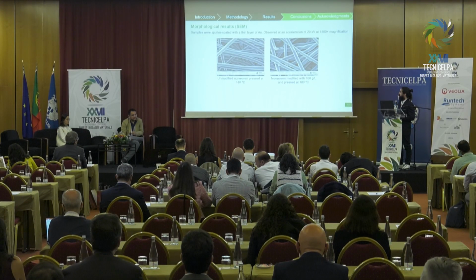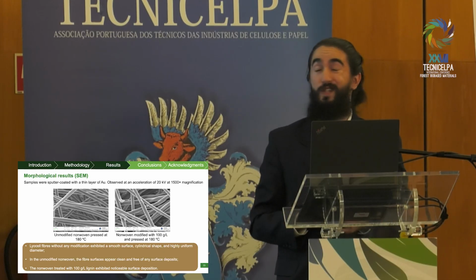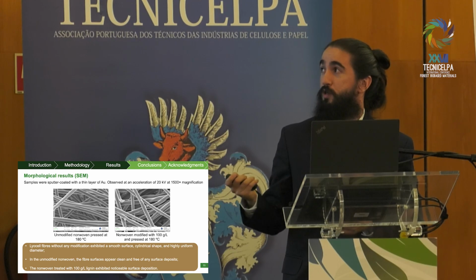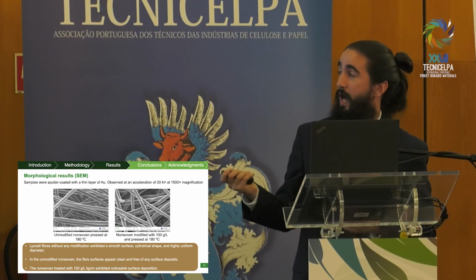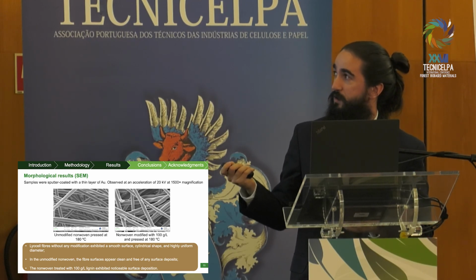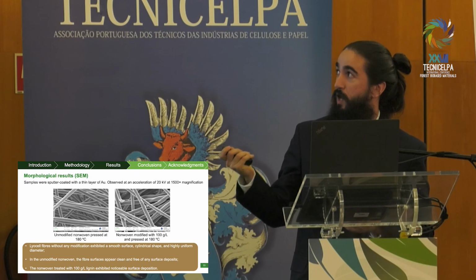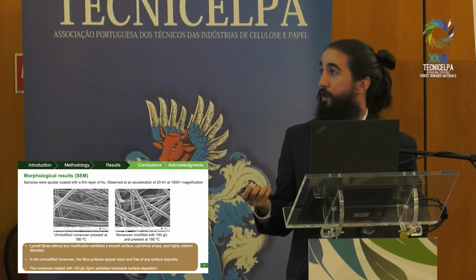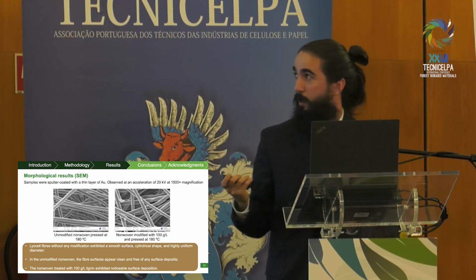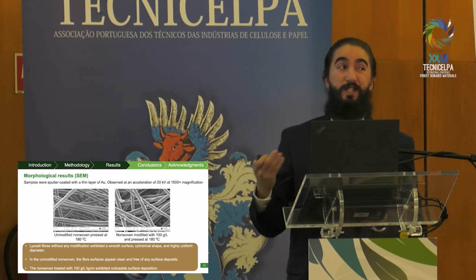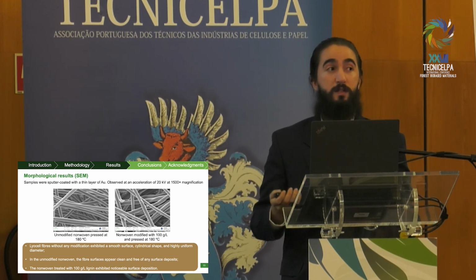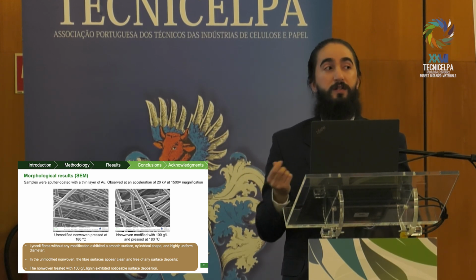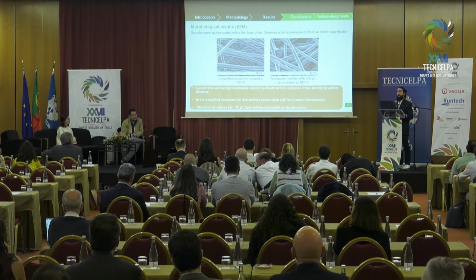As you can see here on the left, the unmodified nonwoven presents the classical structure of lyocell, which is clear, round surface. And when we add the highest concentration of lignin, you can clearly see some deposits on the surface, and possibly even in the interior of our material. Of course, as we increase the lignin, the samples become more viscous, so it might have a harder time penetrating inside the material.